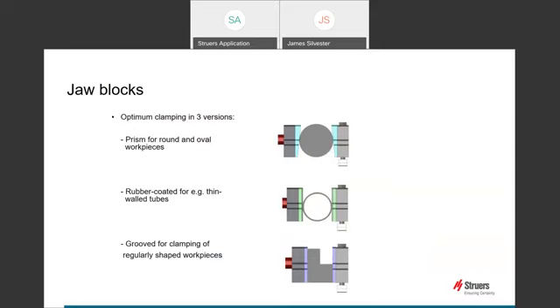Thin wall tubing can easily be deformed during clamping, as often the force needed to hold the sample in place is higher than the strength of the part. The use of rubber-coated jaw blocks allows the rubber to deform around the sample and spread this clamping force over a larger area, helping to prevent damage to the part. Grooved jaw blocks use the grip generated by the grooves to provide more friction to the clamping setup, helping eliminate slipping of the sample. This is especially useful if the sample is hard-faced or made of harder and smoother materials.